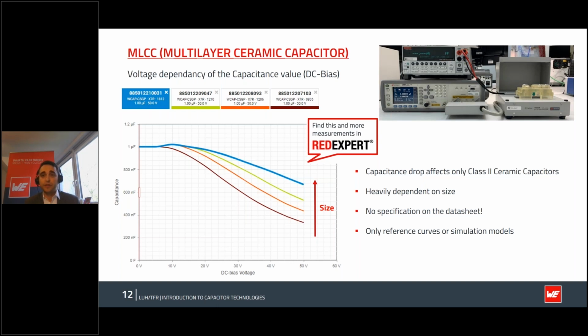So in our current market situation, there's a lot of downsizing going on, which you can do, because a lot of times you can get the same value in a smaller size of MLCC, but this will result in a loss of capacitance due to the DC bias effect being stronger here. So it's very important to take this into consideration. This is something you usually won't find in any data sheet, but some manufacturers do provide this data additionally to the data sheet. And here you can see we show them in our Red Expert.